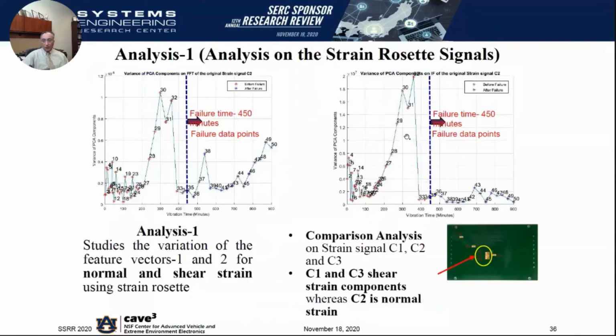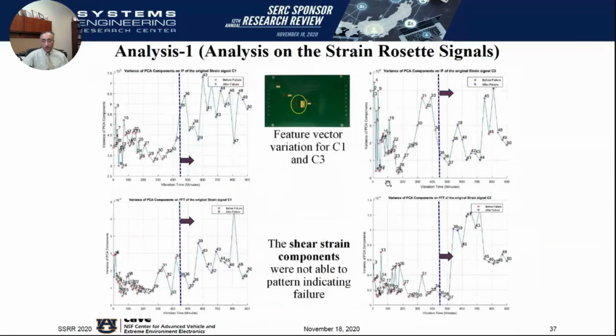So then what we wanted to look at was, what about the shear components? Do shear components provide additional insight beyond the initial insight that we developed using the normal components of strain? So these are the normal component variances. They still look great from the strain rosette, but the shear components actually don't. So our variance actually increases after the failure time. So shear components are not very valuable from our standpoint. Either they increase after failure or they increase much before failure and still spike after failure. So they are not good candidates for feature vectors.